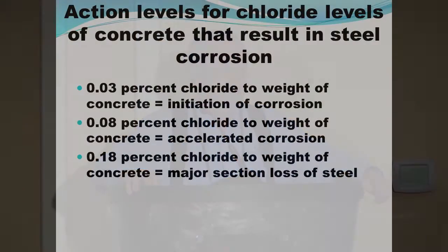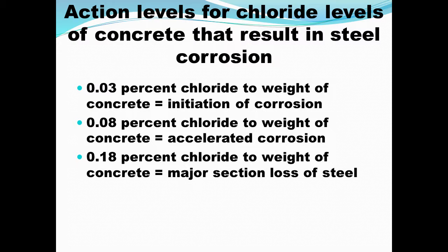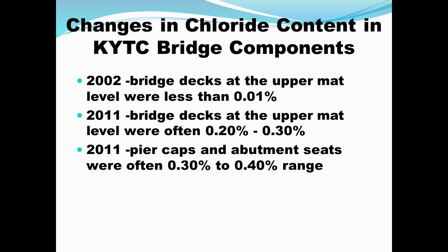As many of you are probably aware, there are action levels for the amount of chlorides in the concrete for steel-reinforced concrete that affect the corrosion of that steel. If you reach or exceed 0.03% chlorides by weight of concrete, you initiate corrosion in the steel. If you exceed 0.08, you're accelerating corrosion, and if you get to 0.18, you're probably getting some severe section loss, a lot of corrosion product on your reinforcing steel.